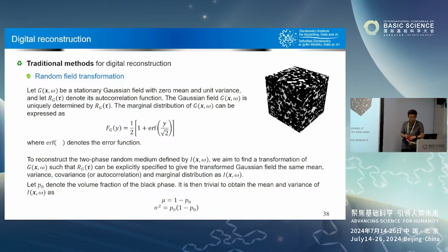In this case, you could say the material, black and white, just two phases, is a continuous value everywhere. If you simply cut that, say everything above a threshold, and use the mean and the correlation as your only target, you could optimize the transformation. It could be a plane, or more clever, maybe a sinusoidal cut, but it would give you the same mean as your reference.